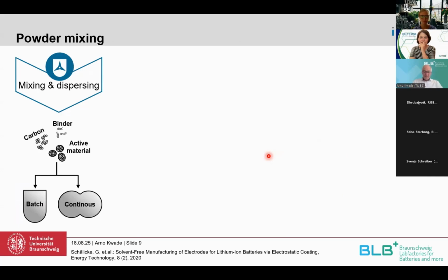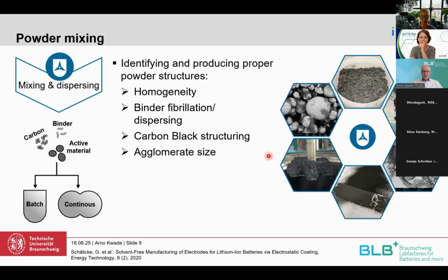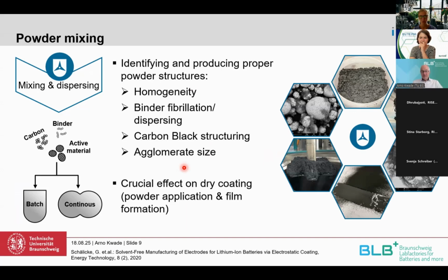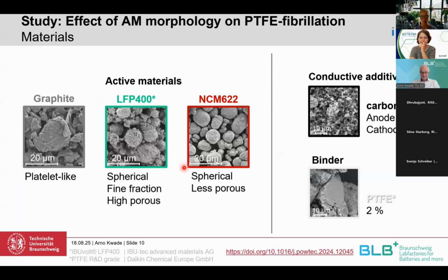Coming to the powder mixing process, as I said, continuous or batch. Important at the end is that we have a homogeneous powder with a good fibrillation of the binder. And also the carbon black has to be structured because there is no wet process doing that afterwards. And the granule or agglomerate size has to be adequate for the following film formation step. That means this mixing step at the beginning is really crucial in this case to get a good dry coating.